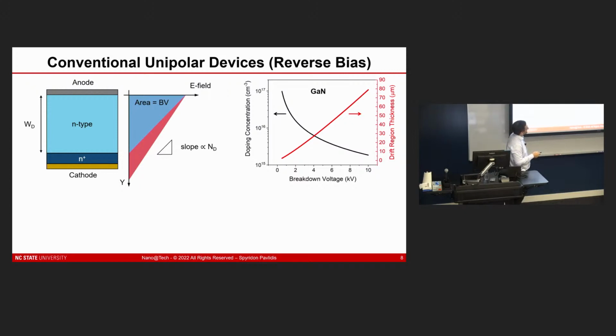So you can see as an example that if you want to make a device that is 5 kV, for example, you have to be into the 10 to the 15 range, which is very, very difficult. You have to have very well-controlled growth processes, control over impurity incorporation. And if you're going to do this for high voltages, you need to be able to grow layers that are tens of microns thick. And so ideally, you don't want to do that with a very, very slow deposition process either. That'll take forever.